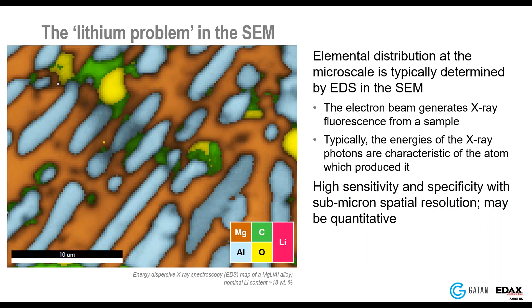Typically we would use a technique called energy dispersive spectroscopy for revealing the elemental distribution of a sample at the micro scale. This is an X-ray fluorescence based process — in the scanning electron microscope we use the electron beam to generate X-ray fluorescence from the sample, and the energy of the X-ray is characteristic of the atom that produced it. It's a technique with relatively high sensitivity and, importantly for this talk, can be performed quantitatively.